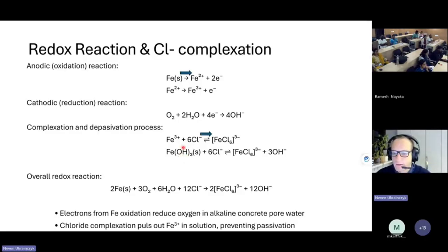At low pH, we increase the solubility of iron hydroxide. Same chemical principle as what we did the first day. But also now we have the complexation reaction of chlorides. Also, if you remember the first day. So we are building this ferrochloride species, complexation species, hexachloride ferrite ions, and they pull this equilibrium to the right, because there is an equilibrium constant. Sorry, I wanted to say that we are pulling this equilibrium to the right.